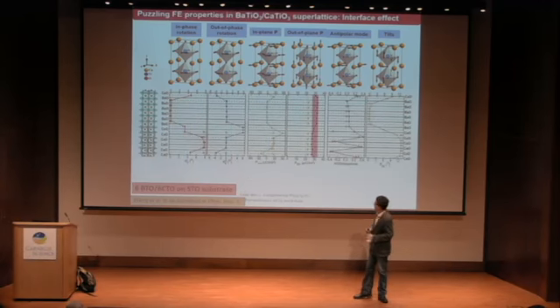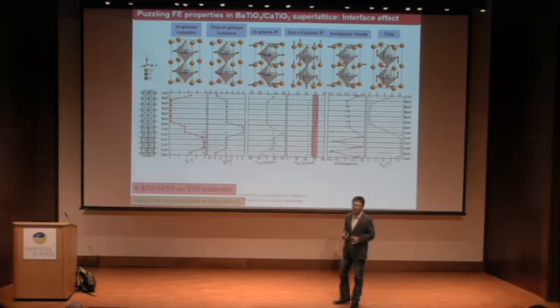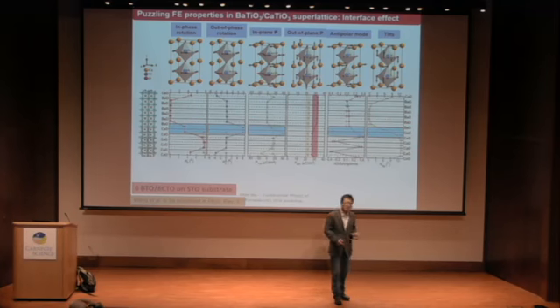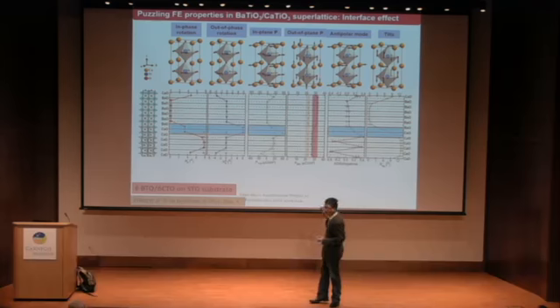So if everything is dominated by bulk effect, you would expect to see this line around 20 in the z direction for polarizations. However, you see around 28. Questions?